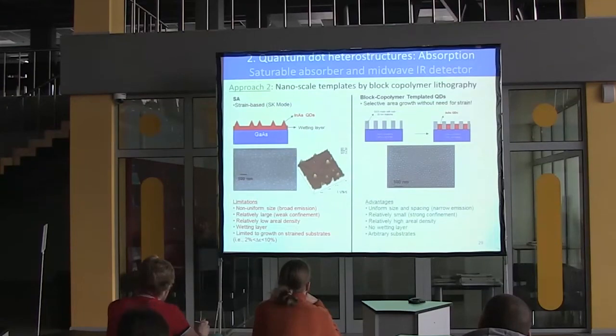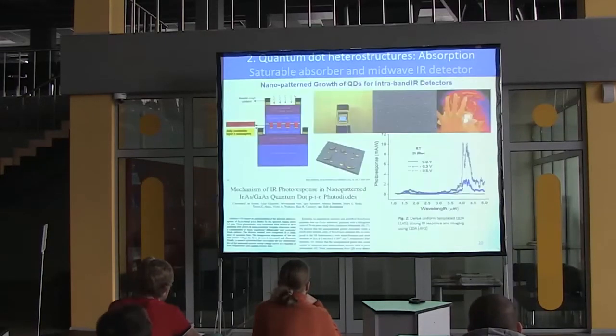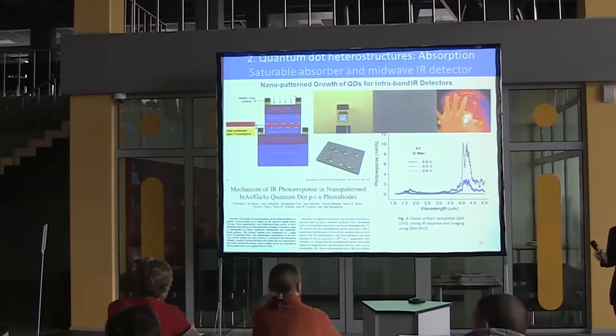So with an incredibly tiny dot, of course, band gaps are huge, right? The level spacings are huge, but really tunable, right? So that's kind of the ultimate way to go. And what do we achieve with that? I'll just kind of explain. These are now inter-subband absorbers. So the principles I told you before, going between those subband states in the conduction band, can tune it. So this is the first excited state kind of transition, and it's massive, it's bigger than band-to-band absorption that I showed you in the previous thing in terms of its effective responsivity. Right? That means response to light, the signal. We built these photodiodes, which are basically so-called pin structures of the big field, and when the absorption occurs, we can extract the carriers out easily, and we can detect with great precision photons. And that's why we made a camera, basically, with those arrays, which you're looking at someone's hand.